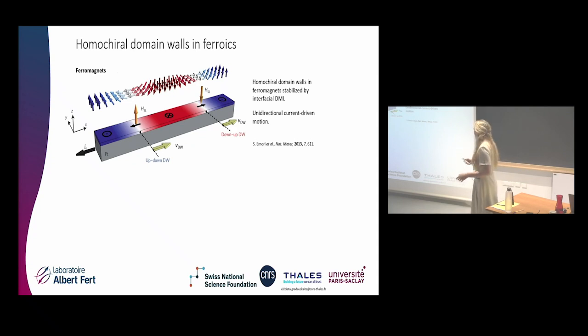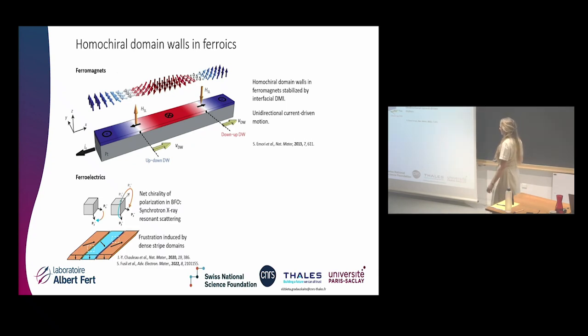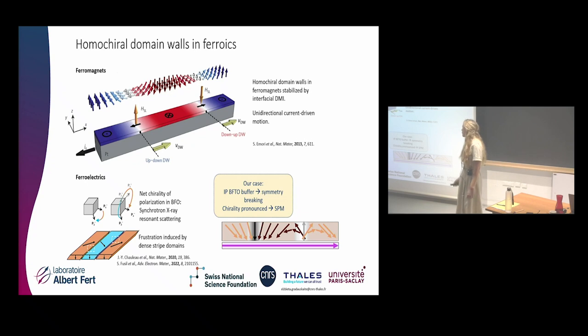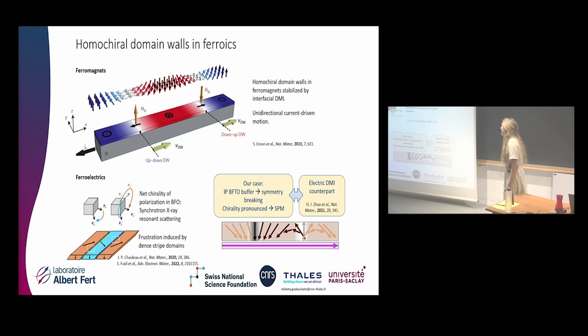But in ferroelectrics, so far, there were not many reports. I think it was only in 2020, 2022, when there were some synchrotron studies picking up on some chirality at the domain walls induced by dense stripe domains, once again in BFO. And in this case, we seem to have something quite similar in the sense that we also see the same homochirality, but here it seems to be induced by this unusual buffer below, unusual strain and unusual electrostatics that we have, and we can even measure in SPM. And that seems to be quite compatible with the electric counterpart to the magnetic DMI that was predicted in 2021 in a theoretical paper. So it seems that these measurements are becoming a new interesting thing in ferroelectrics, that we can look for chirality at the walls as well, not just the magnetic community.